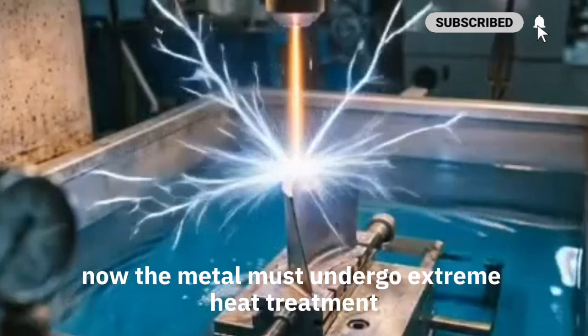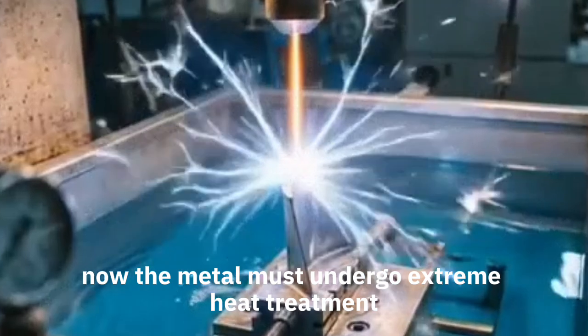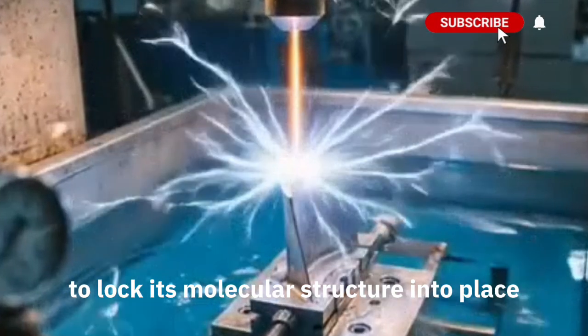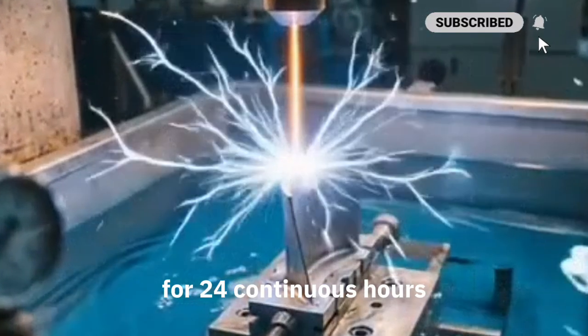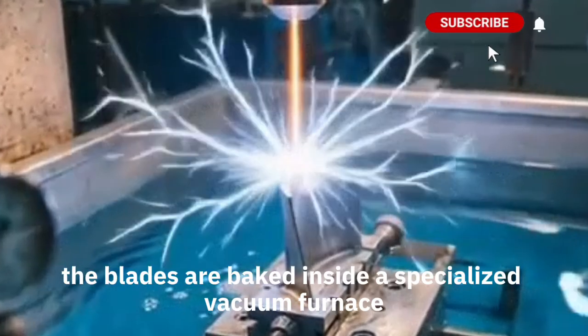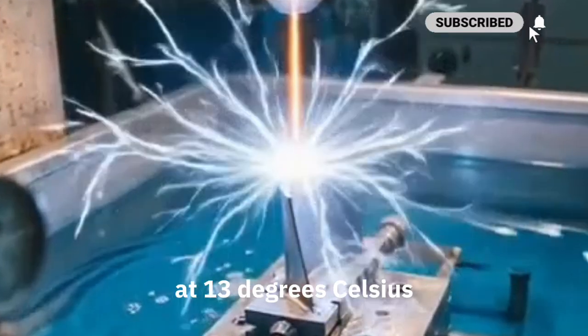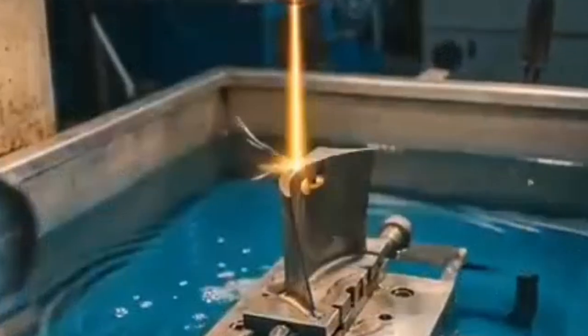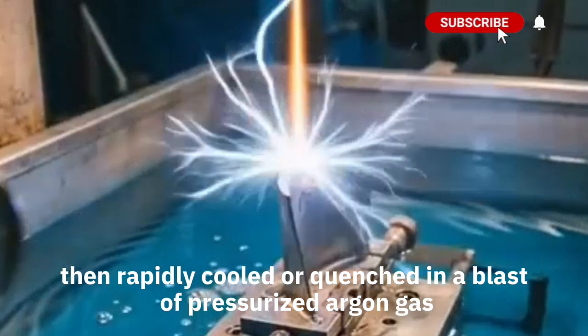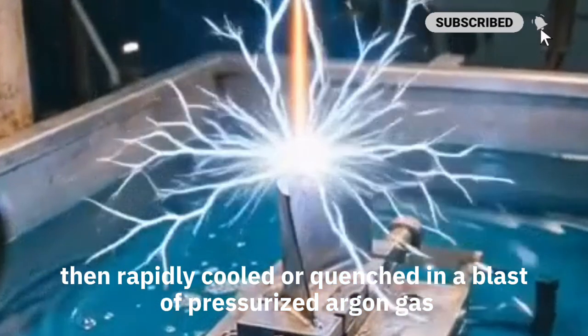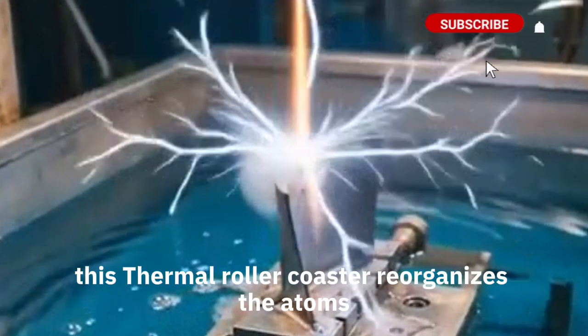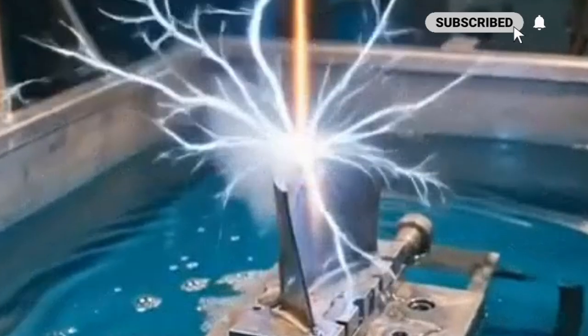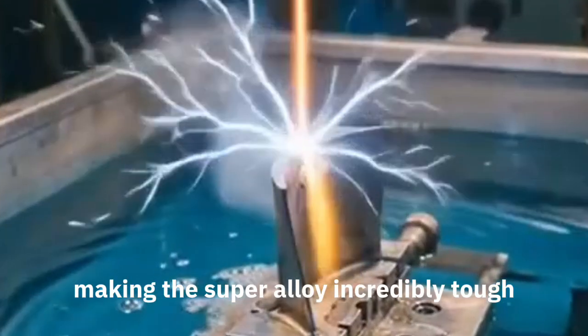Now, the metal must undergo extreme heat treatment to lock its molecular structure into place. For 24 continuous hours, the blades are baked inside a specialized vacuum furnace at 1,300 degrees Celsius, then rapidly cooled or quenched in a blast of pressurized argon gas. This thermal roller coaster reorganizes the atoms, making the superalloy incredibly tough.